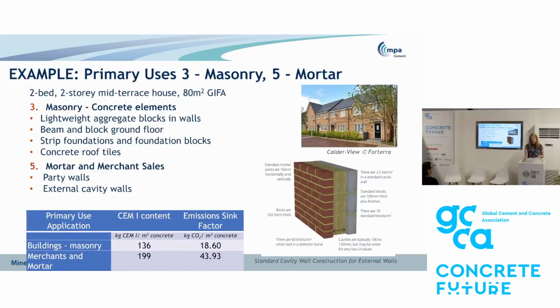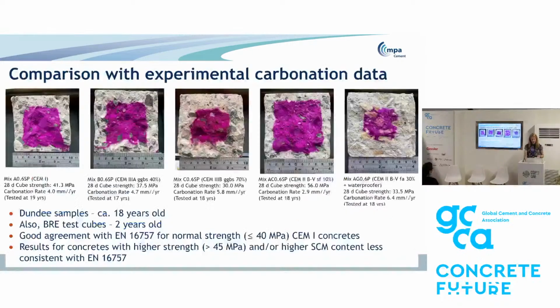So we did that process for all the other three primary use applications as well. And once we'd got those values, the emission sink factors, we compared with this experimental data. So these images show freshly cut concrete cubes, and we've applied a phenolphthalein indicator, which will become colourless at lower pH. So the bits around the outside where there is no pink colour, those are the areas that have been carbonated. And the pink area is the bit that hasn't been carbonated yet.